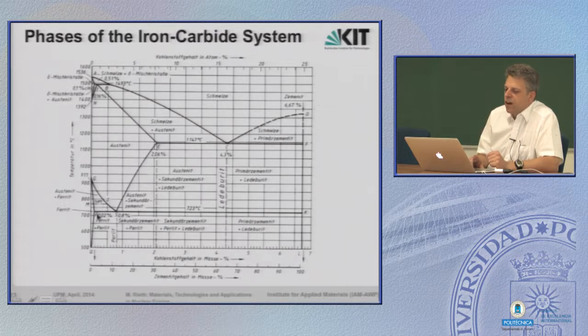The phases, as said, are called austenite when it is FCC structured. It is ferrite, that's this tiny small area, when we have BCC structure. And well, a more complicated phase system, I will also leave over. This is again where we have, at a very high temperature, again BCC structure. Pearlite is a mixture of this eutectoid system. It's comparable to a eutectic system, but it's a solid-solid transformation, so in principle it's the same. This is forming also within this system.